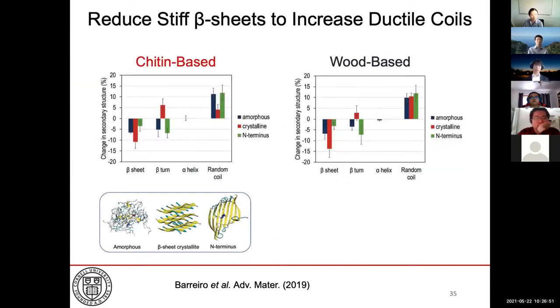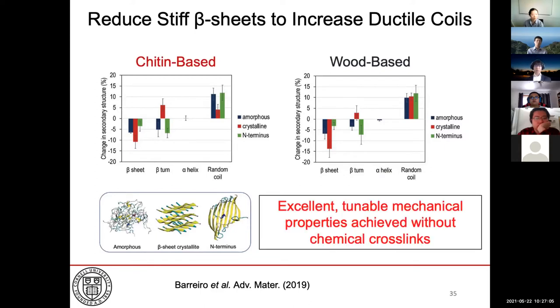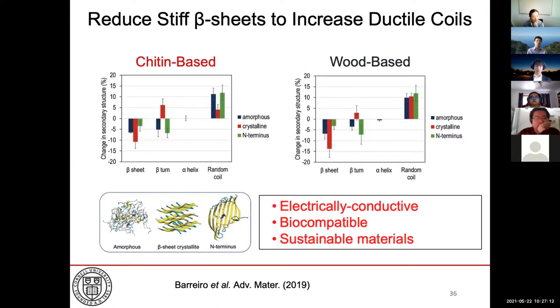And again, we very clearly saw that by adding these different wood-based structures, it actually reduced the stiff beta sheets and increased the ductile coils. And if you recall, these different structures gives different mechanical properties to the silk film. And therefore, we do not just achieve all these properties without any form of chemical cross-linkings, but we also produce electrically conductive, biocompatible, and very sustainable materials.